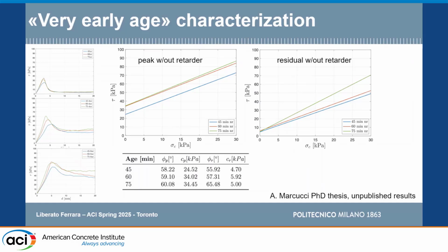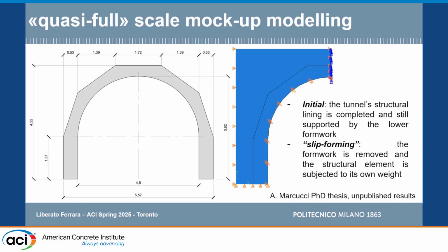And we had results like this. These are the curves. We could identify peak stress and residual stresses, obviously evolving with time. So we were able to identify the representative Mohr-Coulomb parameters for our material. And in the end, with the identified Mohr-Coulomb criterion parameters, we were able to perform an analysis for the transient design situation of our tunnel lining. We exploited the symmetry, so we modeled only half.